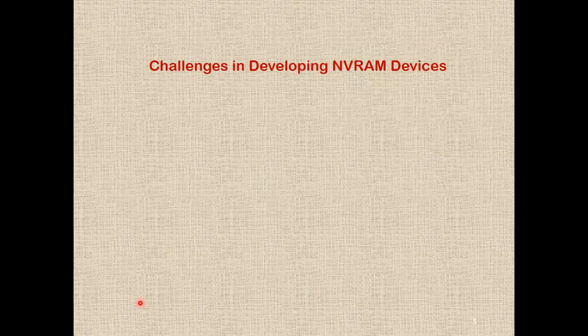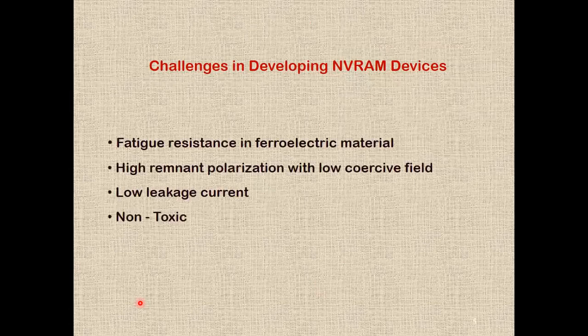The major challenges involved in developing NVRAM devices are: the material should possess high fatigue resistance, it should have high remnant polarization with low coercive field, it should possess low leakage current, and it should be non-toxic.